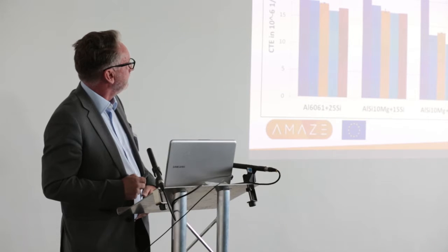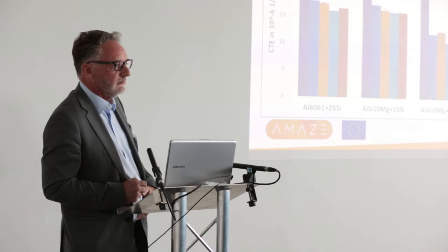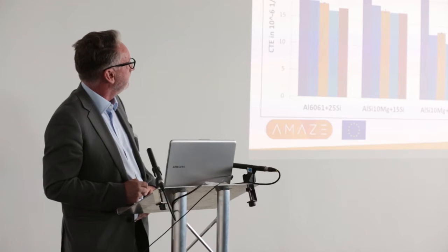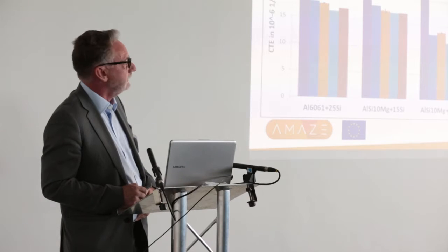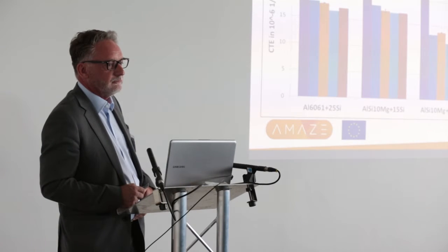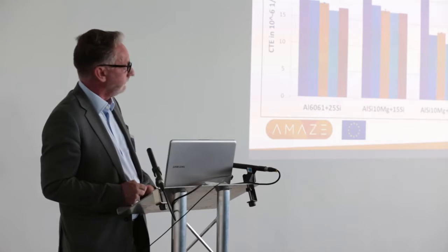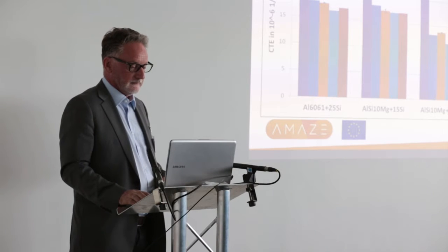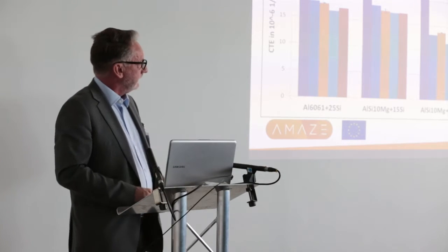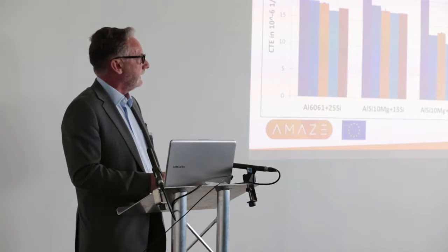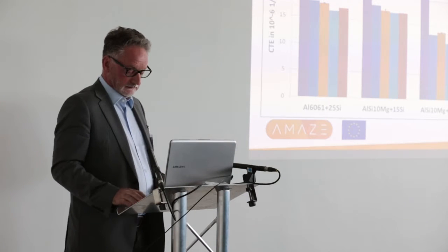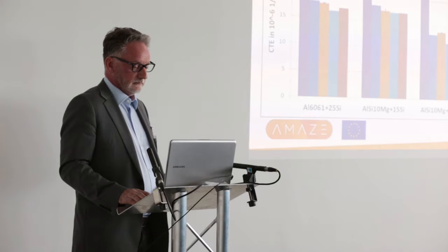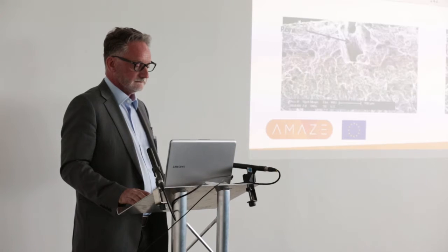That's very interesting, and this compares with the standard Osprey material, which is produced by spray forming, and you can see you get very similar expansion coefficients for these materials. So this is quite a nice alternative way to produce these sort of materials. And it would be interesting to add more silicon still and carry on further down so that we could produce materials with even lower expansion coefficients.